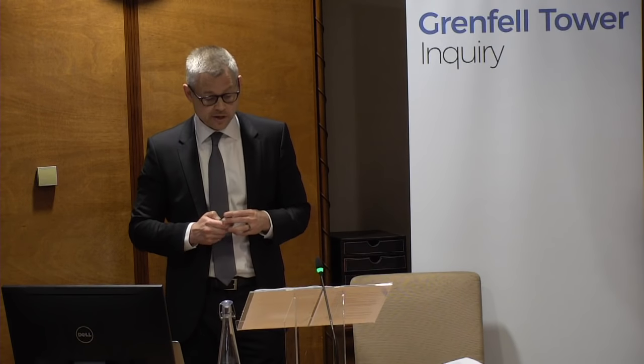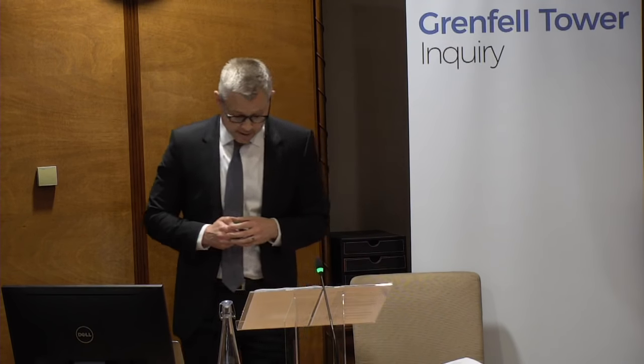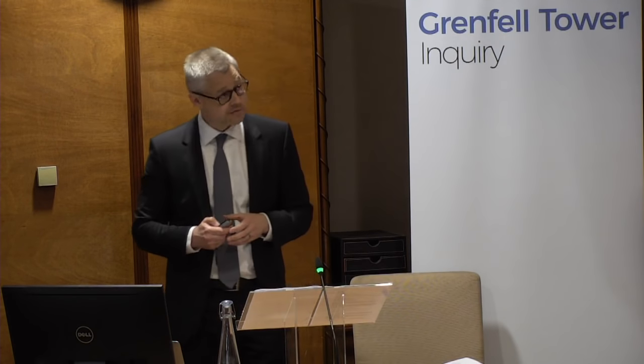My next short video shows downward or opposed flow flame spread on an otherwise identical vertically oriented matchstick. In the case of downward flame spread, the rate of heat transfer to the unburnt material is much less than in upward flame spread, as I've already described. Consequently, the length of the preheated zone is much smaller, resulting in a smaller pyrolysis region, a smaller volume of evolved pyrolysis gases, and a much slower rate of flame spread. Indeed, in this case, flame spread eventually extinguishes rather than continuing to spread downwards. This sequence of events is shown in this short video.